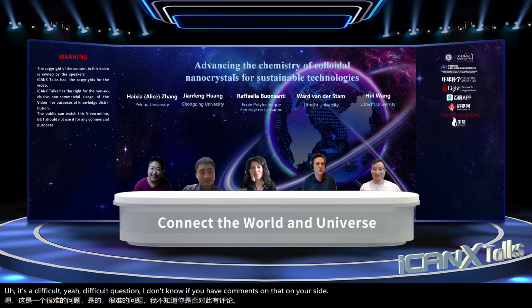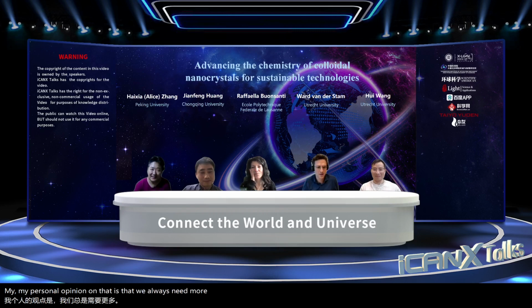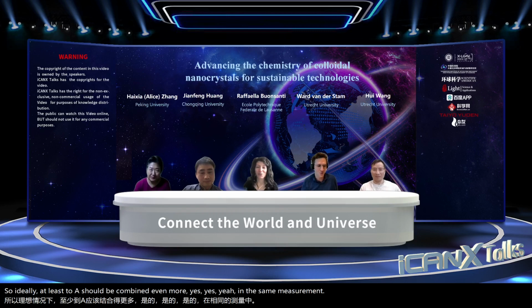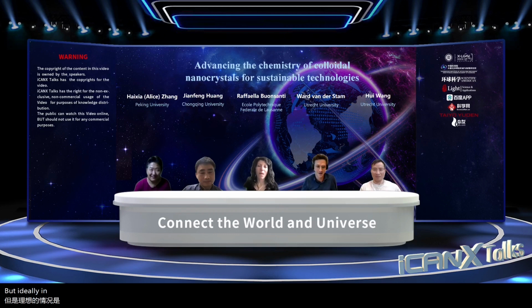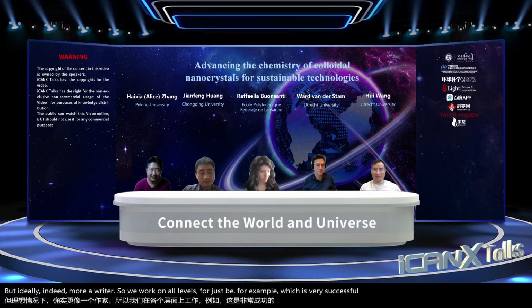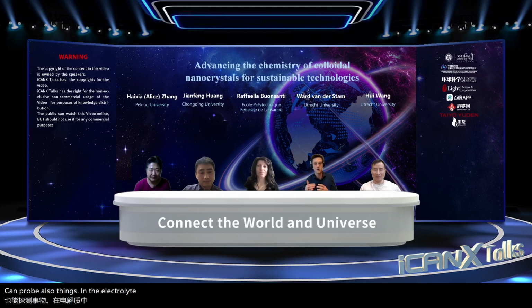So my personal opinion on that is that we always need more techniques. We cannot rely on a single technique. So ideally, at least two should be combined. Even more. Yes. In the same measurement or in the same environment in different experiments. But ideally, indeed, more. So we work on Raman spectroscopy, for example, which is very surface sensitive. We can probe also things in the electrolyte close to the surface, adsorbed at the surface. But it also has its limitations. And you see certain things, but you also don't see other things. And then the same holds for the X-ray techniques.